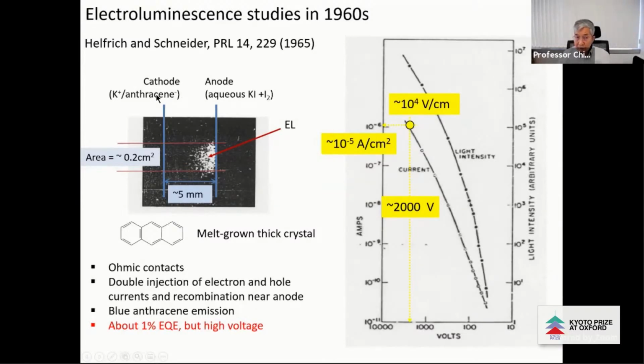They use potassium as a cathode, and then an iodine solution as the anode. This is very well chosen anode and cathode to provide the ohmic contacts. And they demonstrated there's a double injection of the electrons and holes, and then the recombination near the anode. So therefore, the electrons move across and recombine in this region with the holes. And you see the blue light emission.